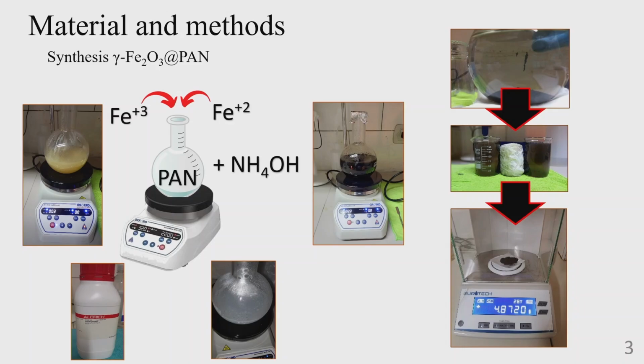It is left to rest for 30 minutes and washed many times with distilled water until a neutral pH is achieved. Finally, it's taken to the heating oven. The magnetic dispersion was stirred for the second sample, functionalized with silica and polyaniline.